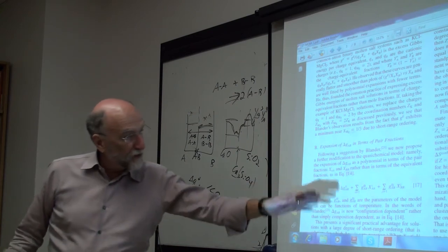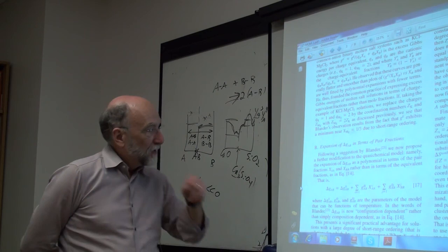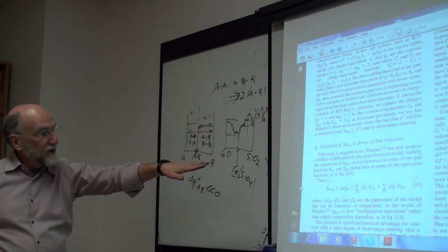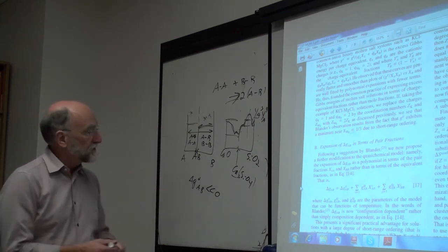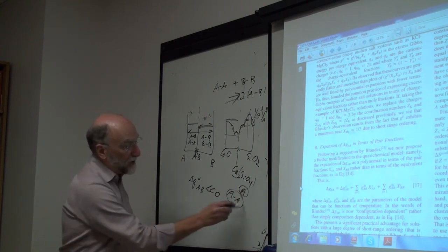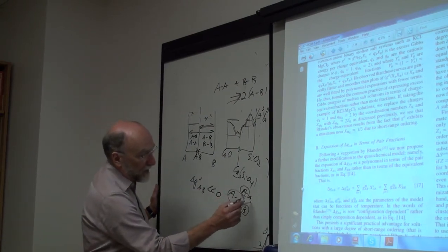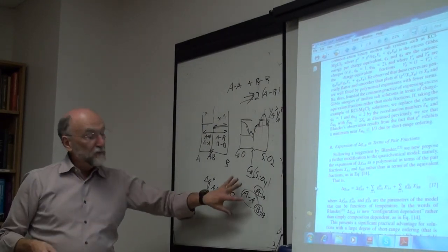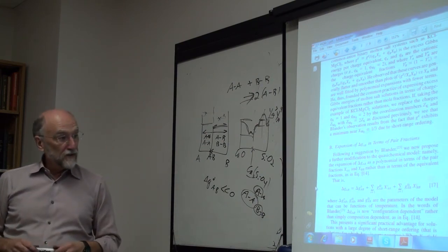Plus, this is actually theoretically a bit better when you're going into multi-component systems too. Remember, when you're doing a polynomial, you're saying the energy of the pairs depends upon the surroundings. So in the polynomial fit, you're saying the energy of your AA bonds depends on the number of A's around it and the number of B's around it. Here you're saying the energy of an AB bond depends on the number of AA pairs around it and the number of BB pairs around it. It's configuration dependent rather than overall composition dependent. I think it makes a little more sense physically.